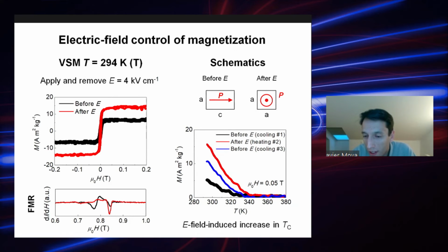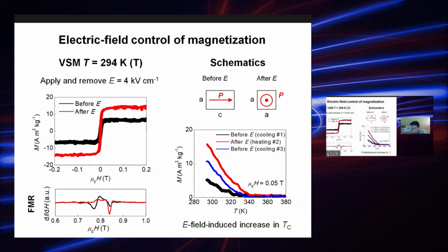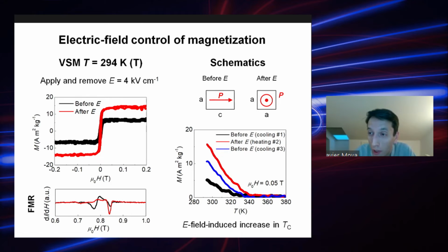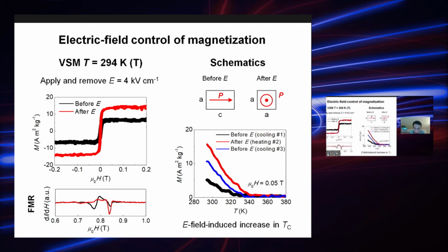We also did magnetization as a function of temperature measurements in order to see potential changes in the Curie point in this material. And you can actually see, I mean, the data is a bit noisy because the signal at room temperature is not so intense. But you can see if you compare the black data with the red data, you can see that there is an increase in the Curie point in the film as well when you apply the field. So this is pointing out all this information to the fact that when you apply electric field at room temperature in this system, you can control the Curie point, which is interesting, actually both from the magnetoelectric point of view and the caloric point of view.